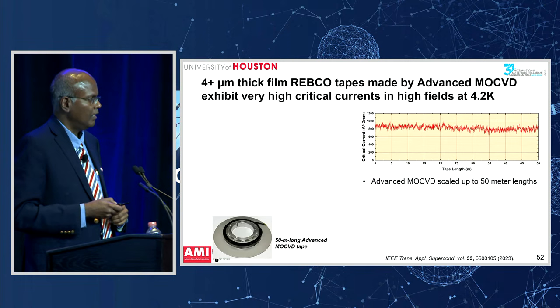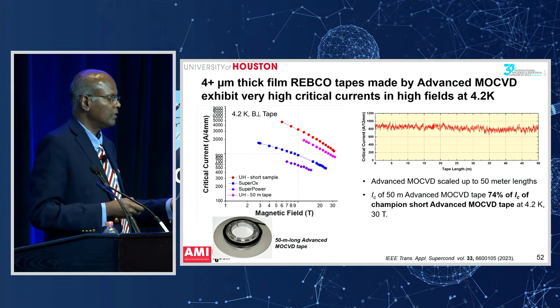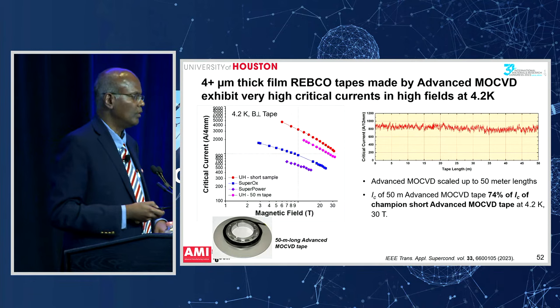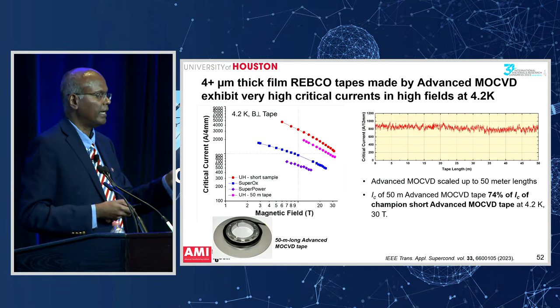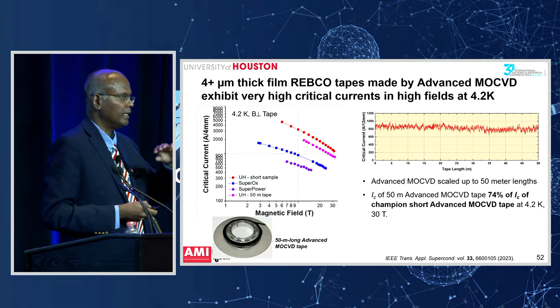All right, so even without the real-time feedback, we're able to now take this method and go up to 50 meters, like I'm showing here, a 50 meter long tape that is shown in this chart. What is shown on the left-hand side is the current carrying capacity in high magnetic fields. The red is what we achieved in a short R&D sample, and the pink is what's achieved on a 50 meter tape.